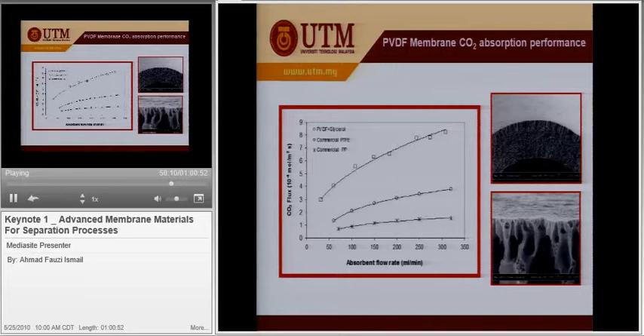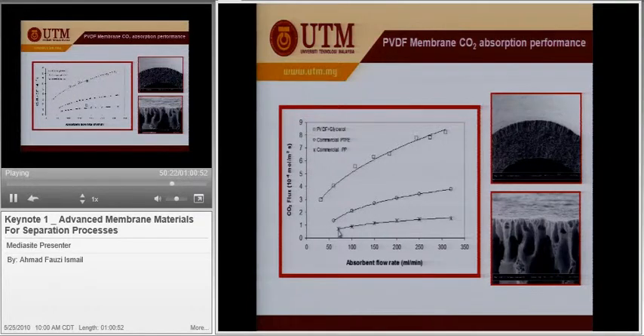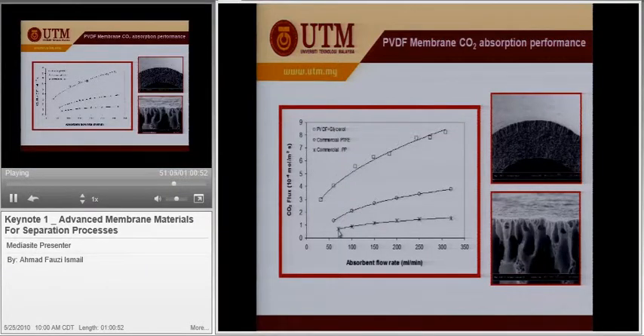So you can see that we developed the technology and compared it with the commercially available polypropylene, and a commercially available PTFE, and this is PVDF with glycerol. You see, our membrane shows very high flux. Flux means very high performance. And here is the structure of our membrane. You can see that it is very porous. Porous means low resistance. Low resistance means high flux, with a very high integrity skin layer, very thin, to ensure high productivity.